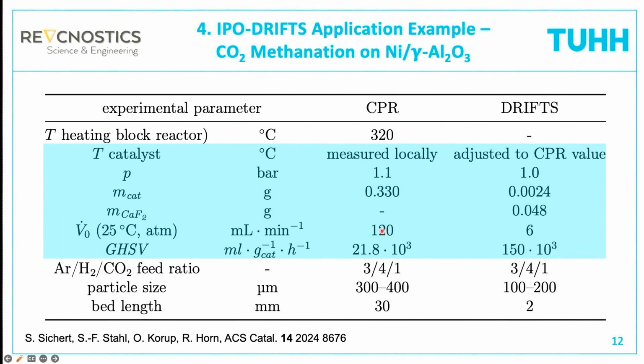And when we convert this now to a gas hourly space velocity, then you see in the CPR we have a gas hourly space velocity of 21,800 milliliter per gram catalyst per hour. And in the DRIFT cell, we have 150,000, so much higher than in the CPR, to make sure that the additional conversion in the DRIFT cell is as small as possible.